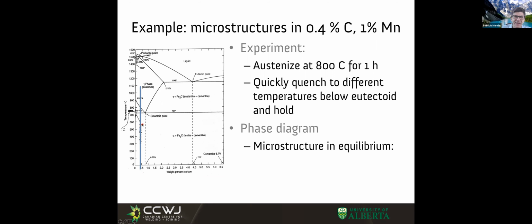This would be relatively high carbon steel to weld, but I chose 0.4 because I have some data on it. And at this composition, as it cools down, we're going to go through the intercritical region. And as we go through the intercritical region, this indicates that thermodynamics says that at some point we should have primary ferrite, right? Because we're going through this ferrite and austenite dual phase field. So we're gonna do the same experiment as before.